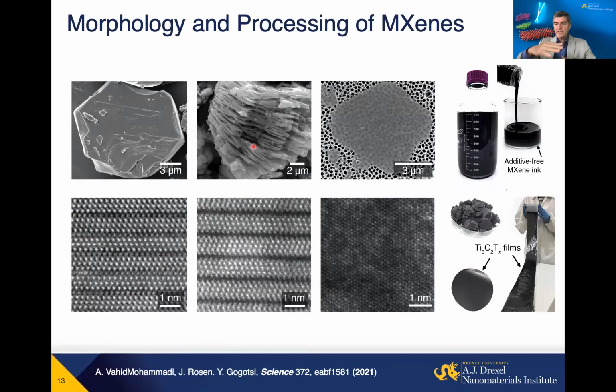So if you intercalate, for example, lithium ions or tetraethylammonium, just like you would delaminate molybdenum sulfide, and sonicate, or sometimes you simply shake the solution, they fall apart into single layers floating in solution because there is negative surface charge, there is repulsion between the layers here. And we get, this is a 1 liter bottle with probably like 10 milligrams per milliliter. It's our kind of stock solution standard of titanium carbide.